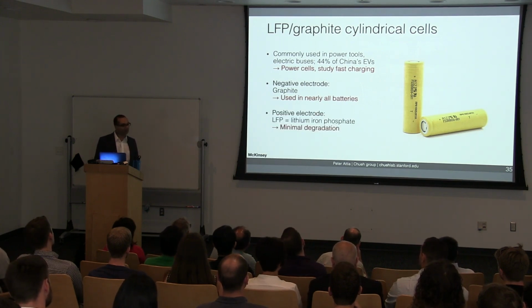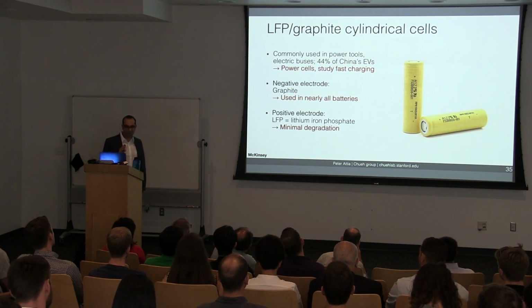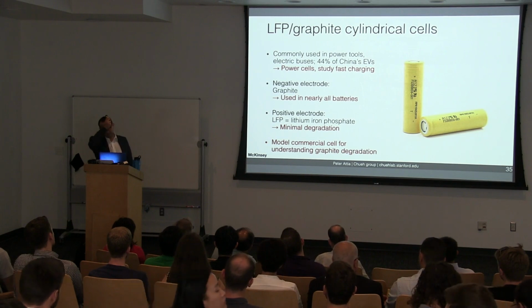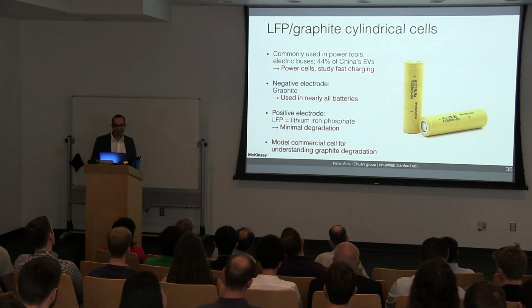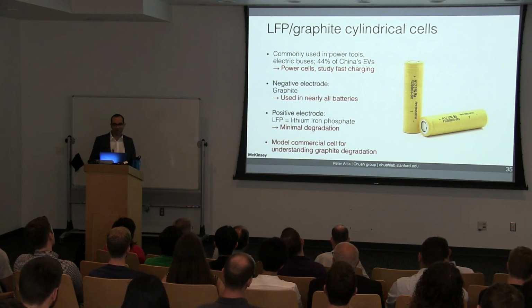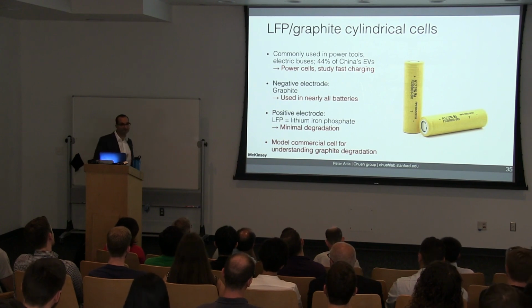The positive electrode is LFP, which is short for lithium iron phosphate. The main thing you need to know about LFP is that it has really minimal degradation. This is actually the real reason why we use these cells. These cells are a model cell chemistry for my work because almost all the degradation in these cells is on the graphite side.